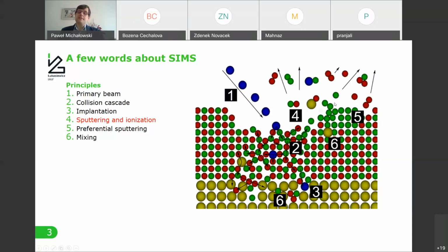This does not represent the actual composition of the sample itself. It was caused by the experiment, so it has to be taken into account that such an effect may hinder proper interpretation of the results. And the other effect, which is also making the life of a SIMS operator a little bit more difficult, is the mixing effect.